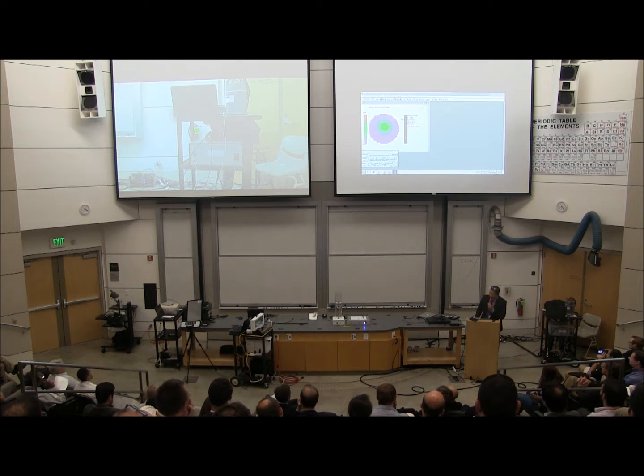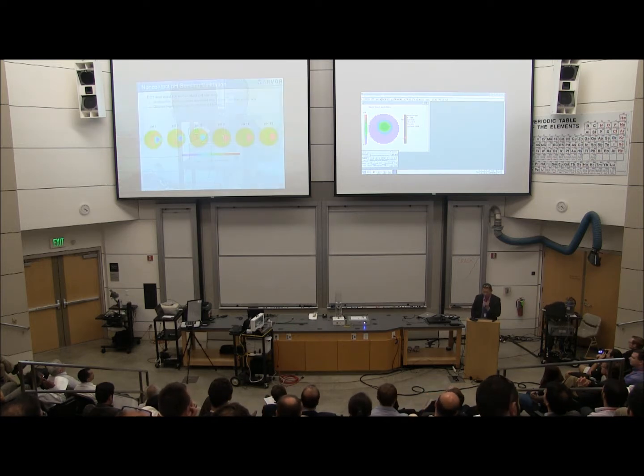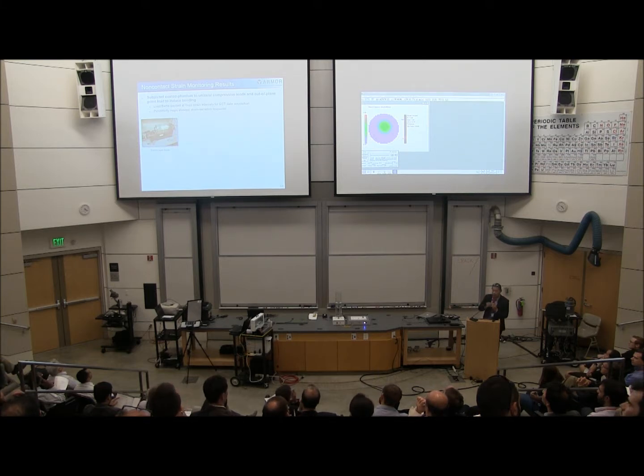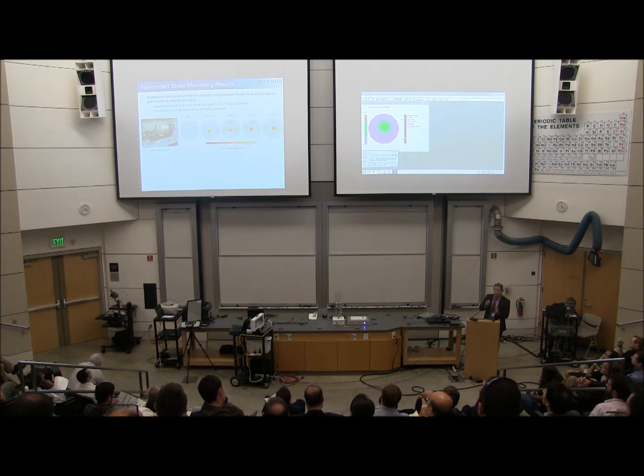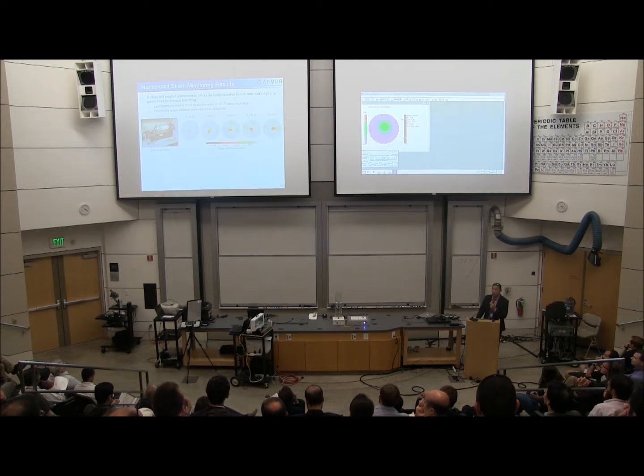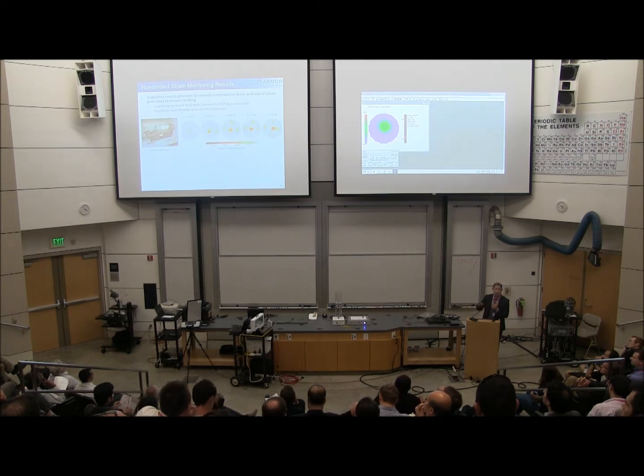Okay, so as Sumit's setting that up, maybe we could switch back to the slide. I'll show the results real quick from what we could get, and then he could show the live demo. So essentially, working with Lintrix and my colleague Michael Todd with their load frame, we've been able to take these rods and apply compression to them. So you can see that this is non-contact, with the rod being imaged using the hardware system. As we apply greater compression, the color of those maps change, indicating the level of strain we're applying to the system. One of the nice things about the load frame is that it's easily configurable.